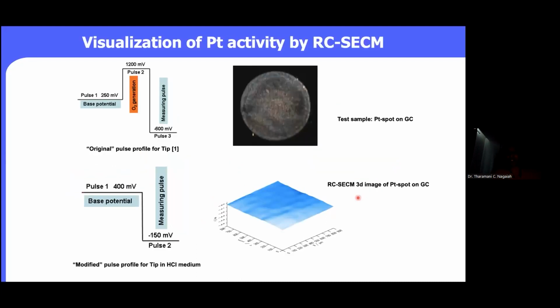So now coming back to the HCl, that means we are utilizing this technique to understand and to establish the stable catalyst here. What we have taken here is a test sample, platinum on the glassy carbon, because we know that for oxygen reduction reaction, platinum is a standard catalyst. However, we cannot apply this pulse profile in this case. The reason is that if we apply the 1200 to generate the oxygen, we are again invoking the chlorine as well. So therefore, we need to modify the pulse profile. That means we are not applying the 1200 and we are applying only the base potential and only measuring.